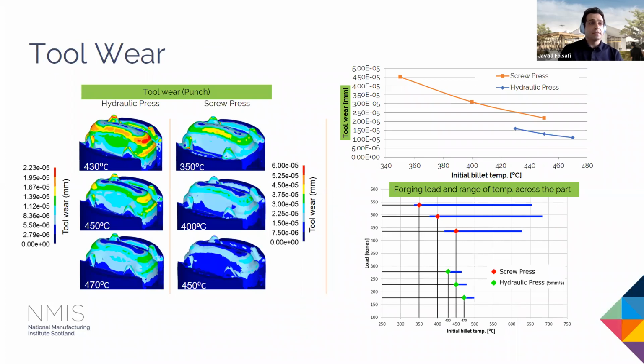In terms of some of the detailed studies, we carried out a sensitivity analysis to analyze the impact of temperature on the tool wear. Here we've got a punch wear map at the left-hand side at various initial billet temperature. On the right-hand side, at the top, you can see the trend. The higher flow velocity, along with the higher pressure in the screw press, has resulted in more tool wear. You can see that in the orange line. And then as we increase the forging temperature, tool wear starts to decrease. That's because the material flows easier. And also there are some other features associated with that, including the pressure, etc.